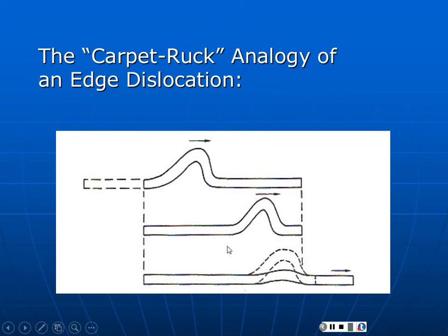Now, this is a dislocation. What is a dislocation? It's an extra half plane of material packed in where there's no room. So, in this case, you're overcoming friction, not all the bonds at once, but by breaking the bonds locally and then laying things back down again. Okay?